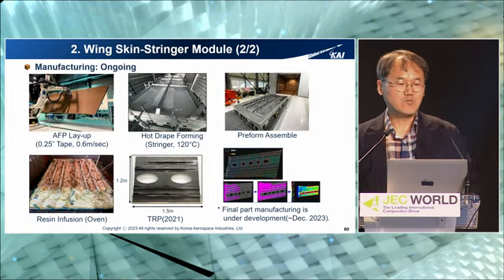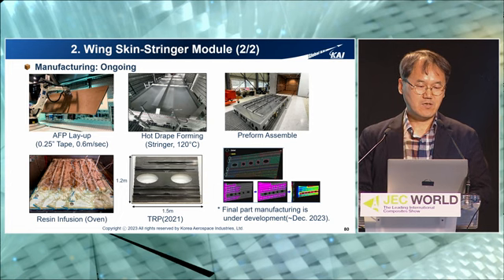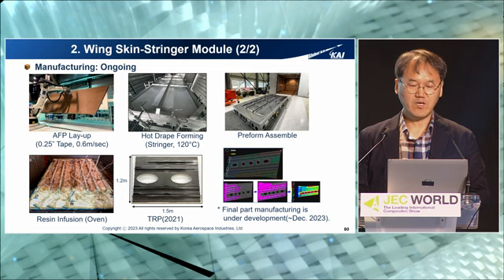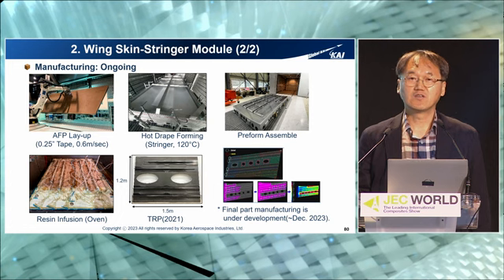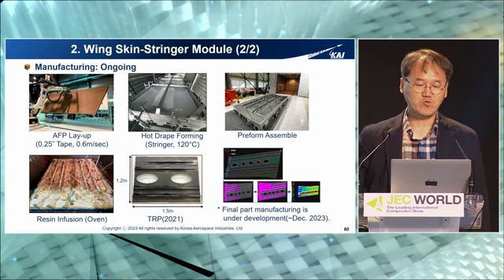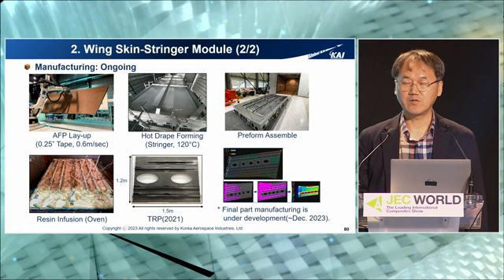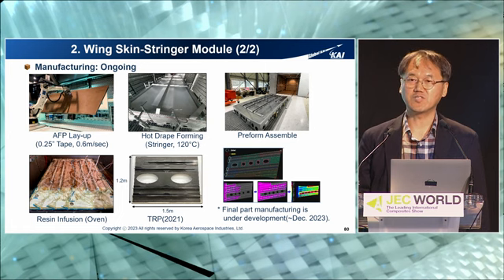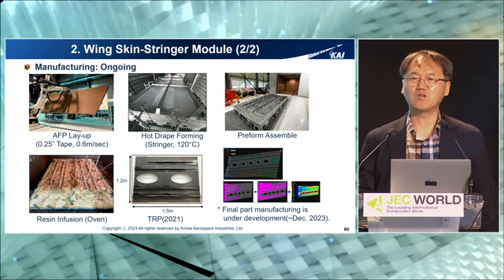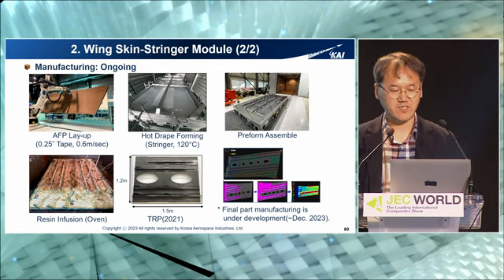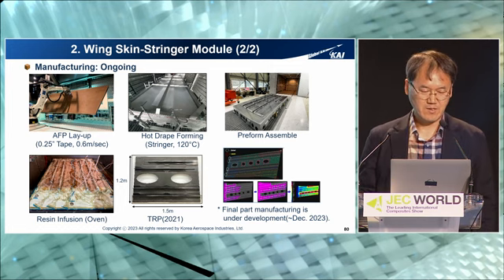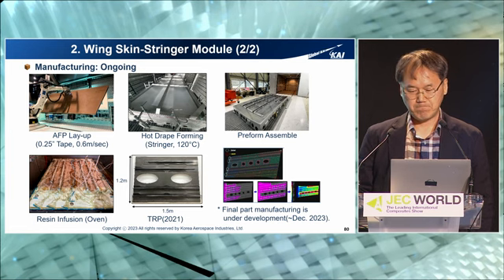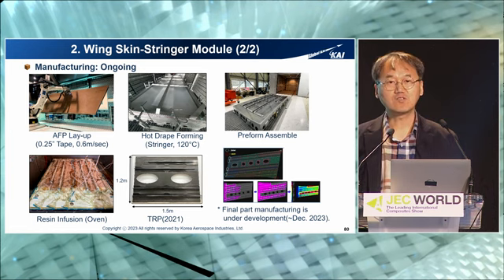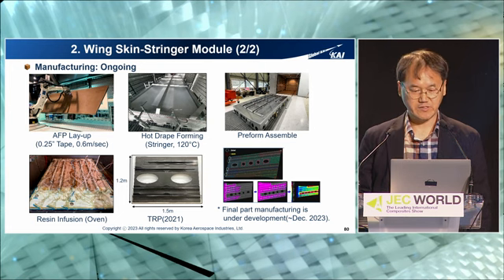This slide shows the manufacturing process. The AFP machine speed was 0.6 meter per second. You can see the hot drape forming pictures. The difference from the previous one is the relatively lower temperature hot drape forming, which means 120 degrees Celsius hot drape forming compared to the 170 or 160 degrees Celsius hot drape forming. And this also will be completed at the end of this year.